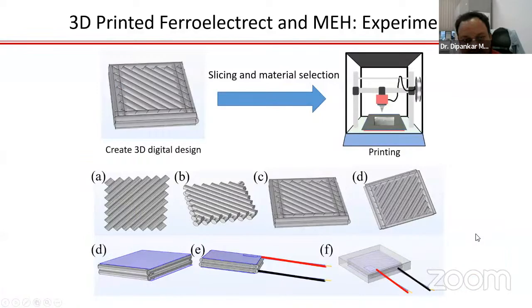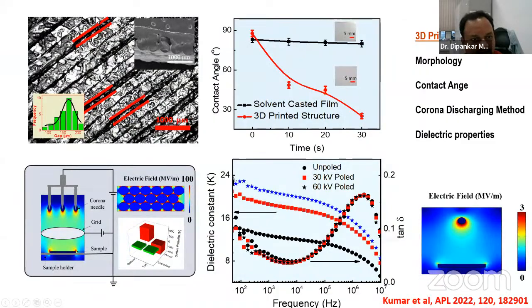Okay, so the charge displacement is possible to make much higher. So use the 3D printing system to make the electrode structures. Okay, and we have shown that if we charge through the corona poling, high voltage poling, then we can change many things like morphology, contact angle, dielectric property.